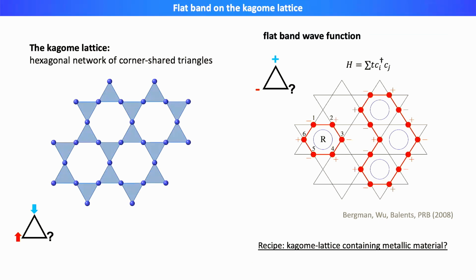So here, it's also found to be able to support the flat band states, where I'm showing you two different real space eigen wave functions of the flat band states. For the minimum real space eigen wave function, you again have this six-site state with alternating sign patterns. And this larger loop here is actually a linear superposition of this smaller loop that's located on three adjacent sites.